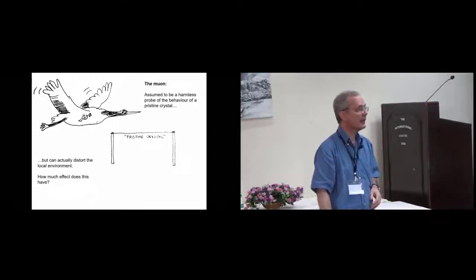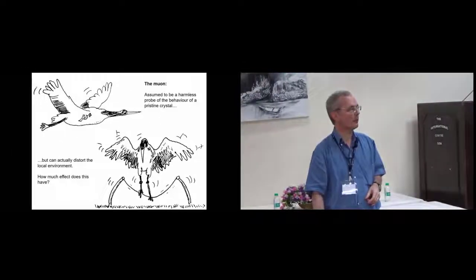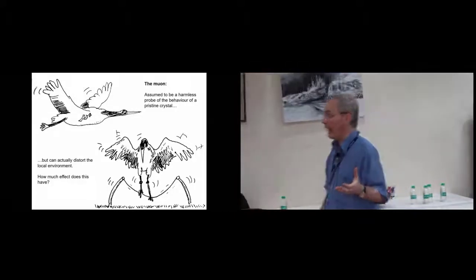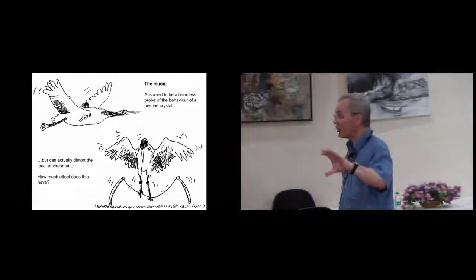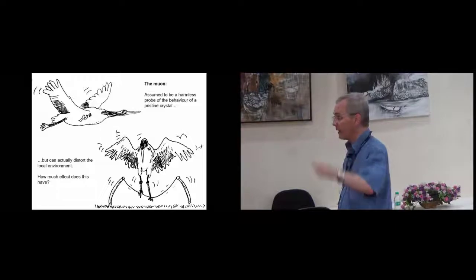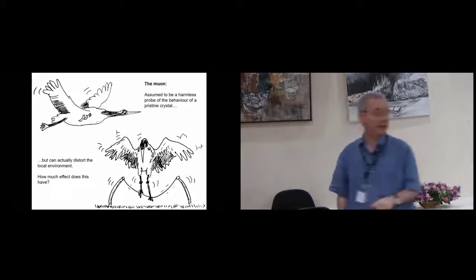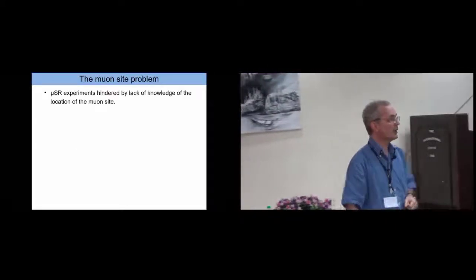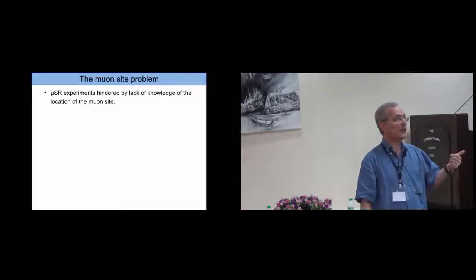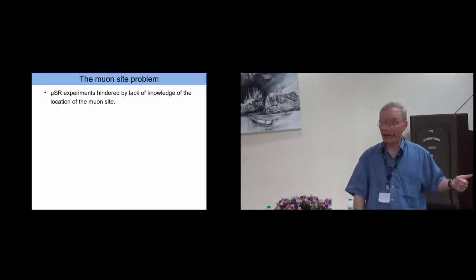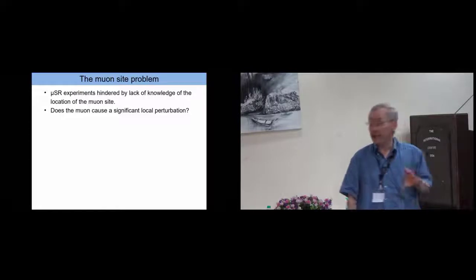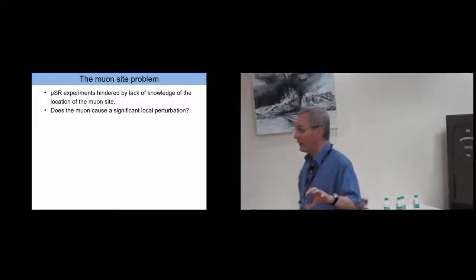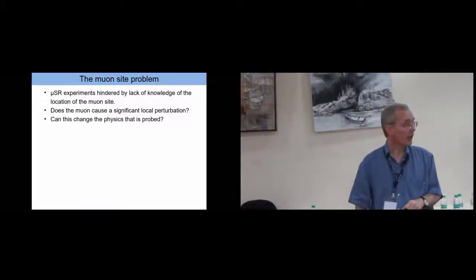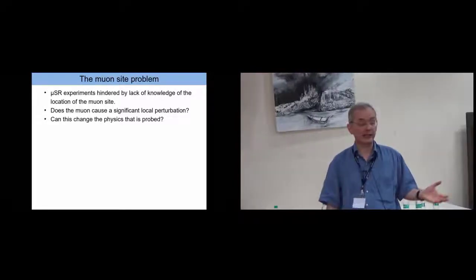But what happens if the muon, when it's probing the sample, actually perturbs it? How much effect does the muon have? Is it really measuring an intrinsic property, or is the presence of the muon very disruptive? So this is really the problem. First of all, we don't always know where the muon is. Secondly, does it give a significant perturbation? And can that change the physics that's probed?